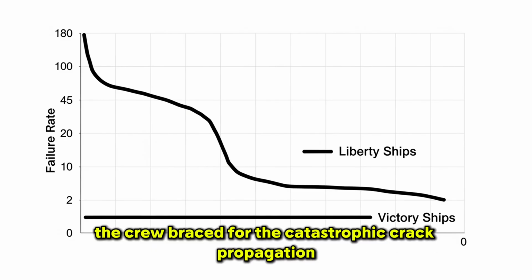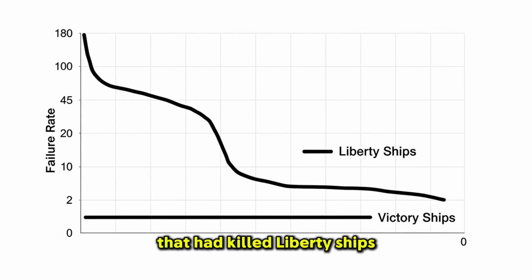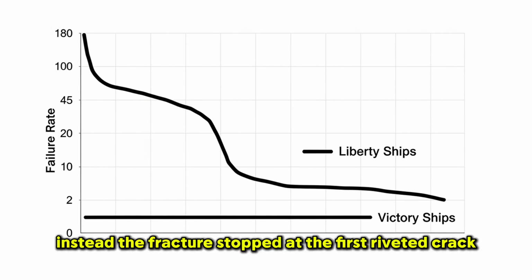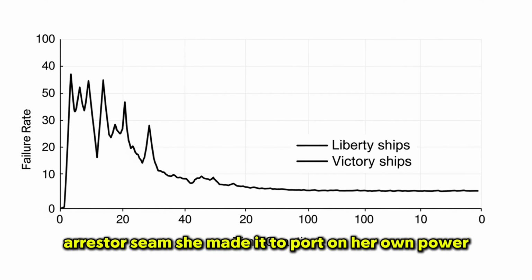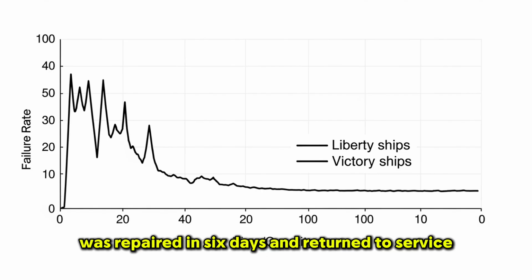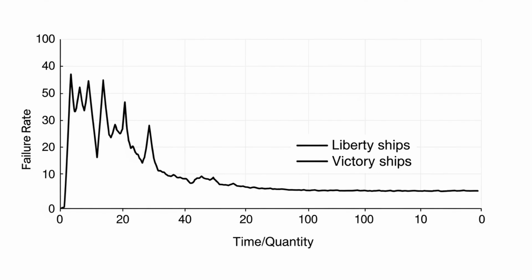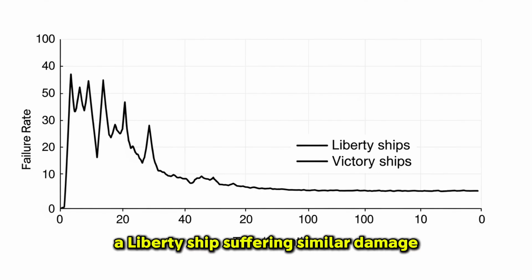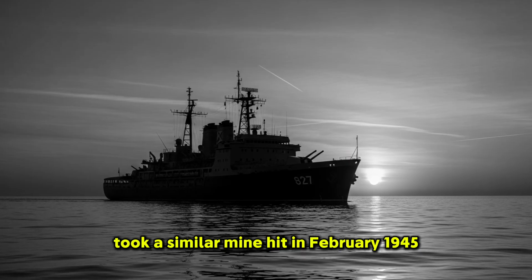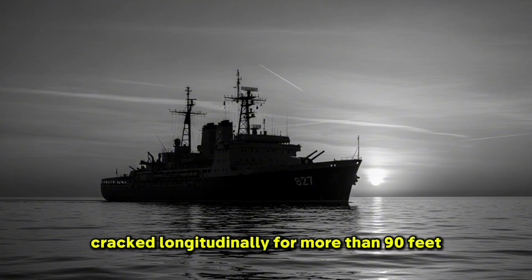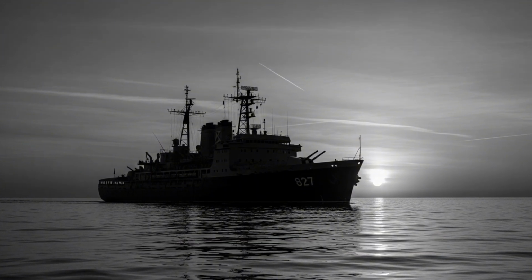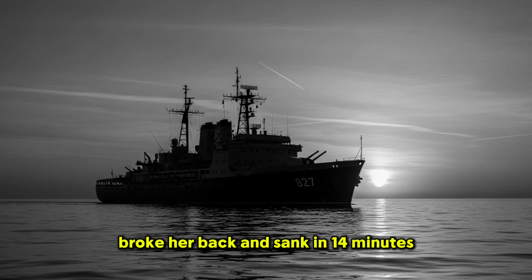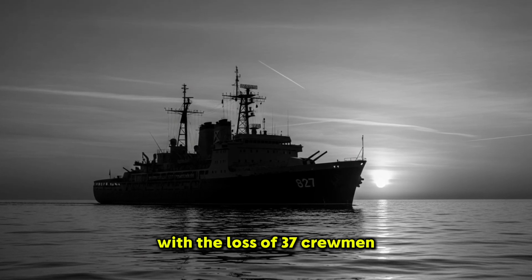The crew braced for the catastrophic crack propagation that had killed Liberty ships. Instead, the fracture stopped at the first riveted crack arrestor seam. She made it to port on her own power, was repaired in 6 days, and returned to service. A Liberty ship suffering similar damage, the SS Richard Hovey, took a similar mine hit in February 1945, cracked longitudinally for more than 90 feet, broke her back, and sank in 14 minutes with the loss of 37 crewmen.